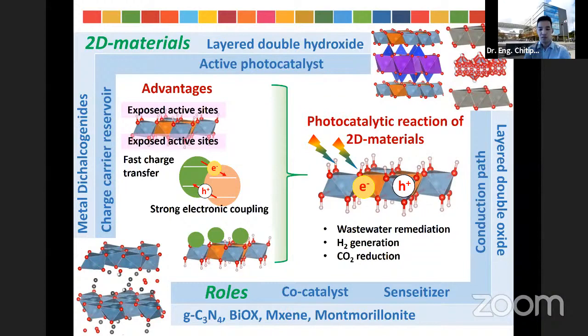All of them, natural or synthetic materials, can be utilized in many applications, for example as co-catalyst, sensitizer, conduction path, or photocatalyst. The most promising property of 2-dimensional materials is the large exposed active site, which can receive more light and has a larger active surface area for the reaction. Moreover, 2-dimensional materials can provide more surface contact with other semiconductors or photocatalysts in the composites, as I show in this slide, in the green one and orange one here.